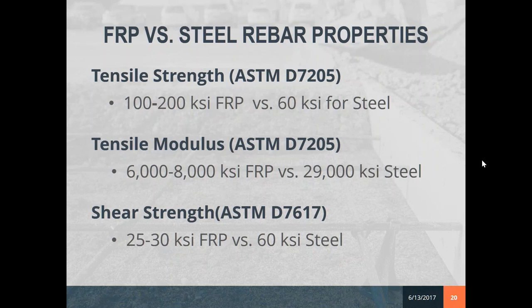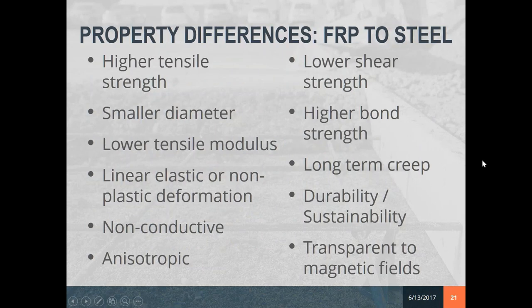ACI code allows you to bundle up to 4 bars in order to increase some of your stiffness and some of your shear strength, or you may have to go to a larger diameter bar. In most of your flat work, because of the strength of these type of materials, you can actually go the other way and use a smaller diameter bar. So if you have a number 4 listed on a job, generally you can use a number 3 FRP because of its material properties, and it works very well. A lot of times if you have a number 3 bar at 12-inch spacing, you could actually go to an 18-inch spacing when you're running through the formulas and looking at the design parameters. Again, you just have to understand the properties of the materials that you're designing for, and deal with them accordingly. So here's some of the property differences.